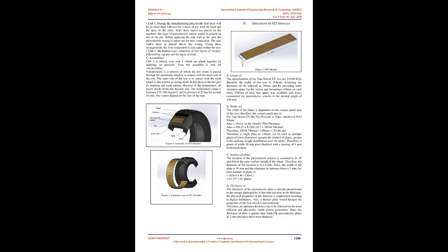Because of the temperature, all layers inside the tire become one. The temperature range is between 170–200 degrees C at a pressure of 22 bar for around 10 minutes. The values depend on the size of the tire.